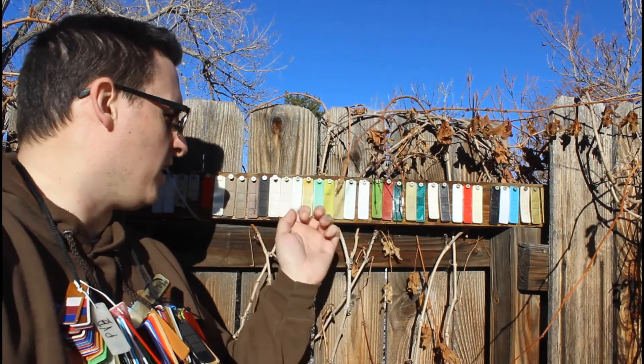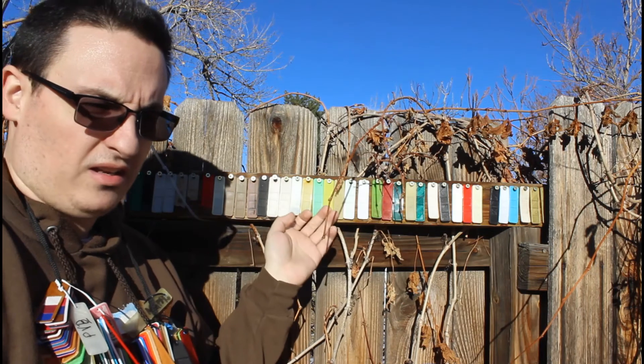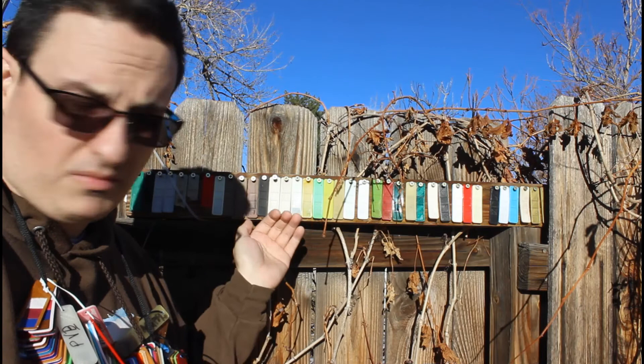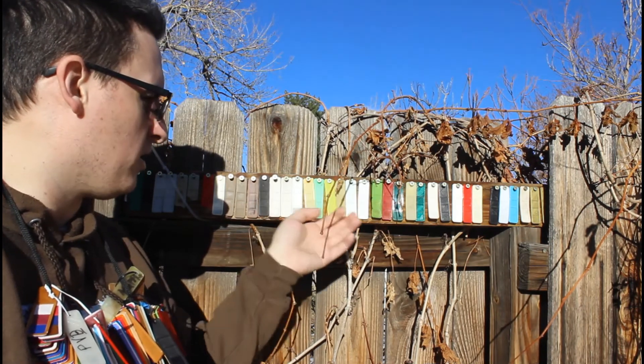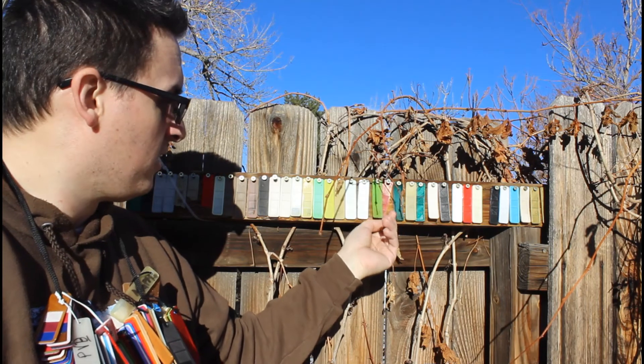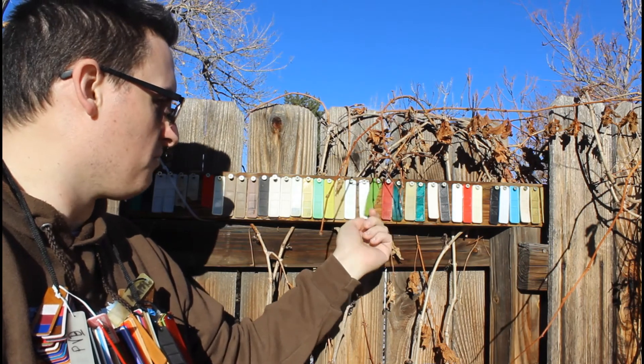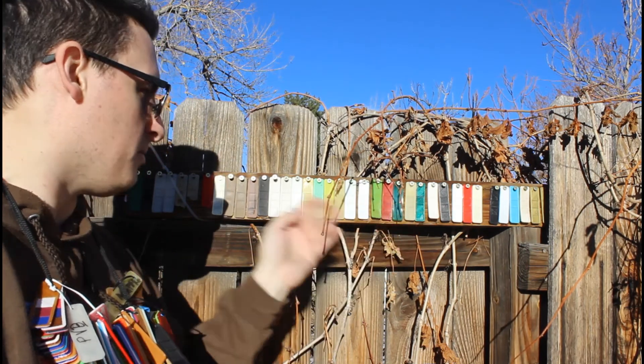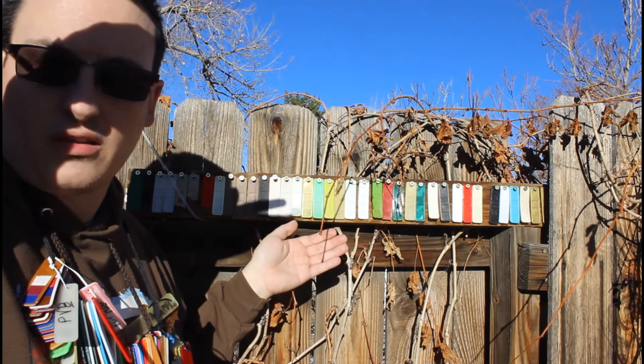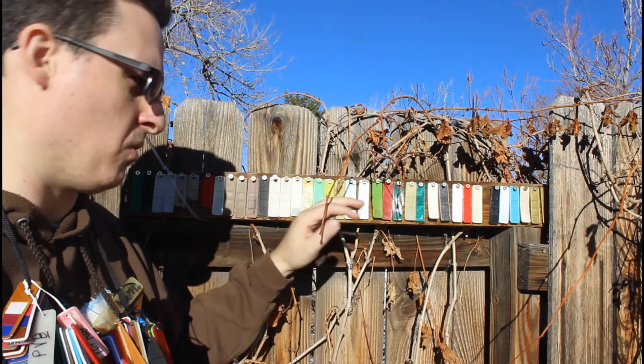Overall, the main effect of leaving these outdoors has been that they've definitely faded. Some of the composite ones have definitely changed their tint and color. The interesting ones are the TPUs — the Ninja Flex and Semi Flex — because even though they've lost a little bit of color, they're still flexible after three years of outdoor exposure. Some of these you could use in something like a garden or for some outdoor application, just be aware that you're going to lose color.